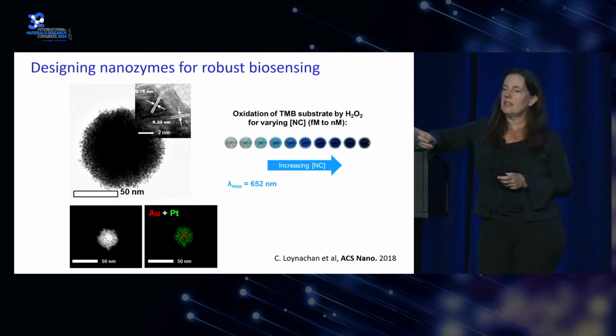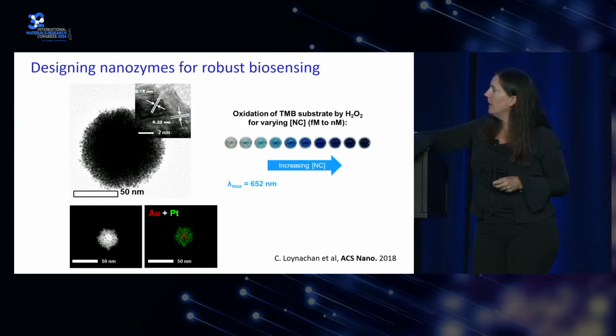Because the tests that existed at the time when we did this work were not sensitive enough to detect virus infection within a couple of days. You needed to wait several weeks till your body had produced antibodies to HIV. And what Colleen did was to develop these particles that have a gold core and a porous platinum shell.